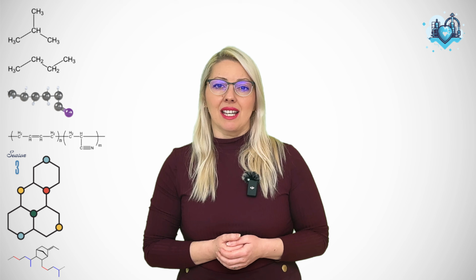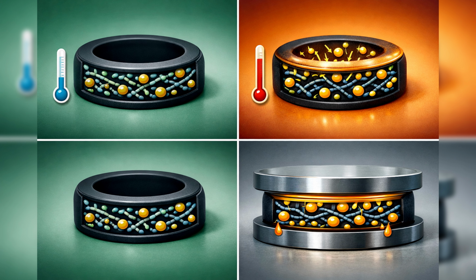Temperature ties everything together. Higher temperature increases chain mobility, diffusion rate, and free volume. A compound that looks stable at room temperature can start bleeding oil at elevated temperature simply because both kinetics and thermodynamics shift. This is why oil migration problems often appear in service rather than during lab storage.